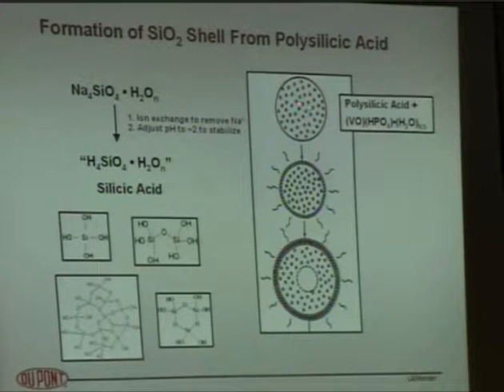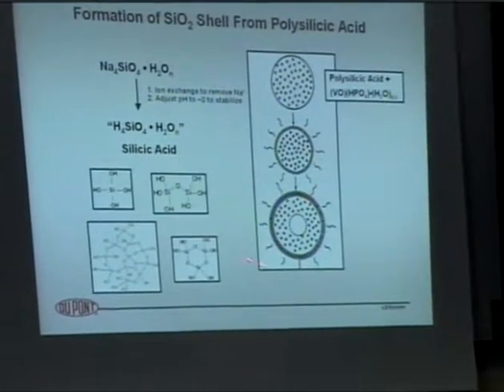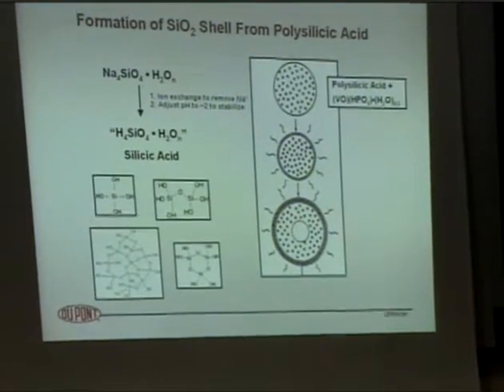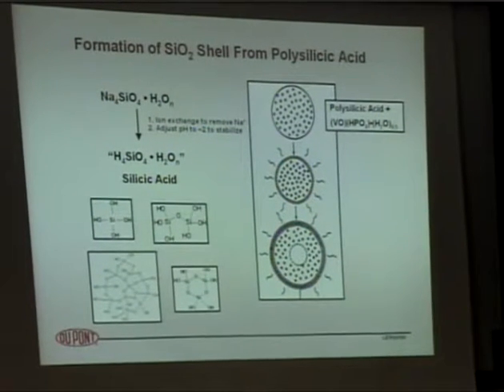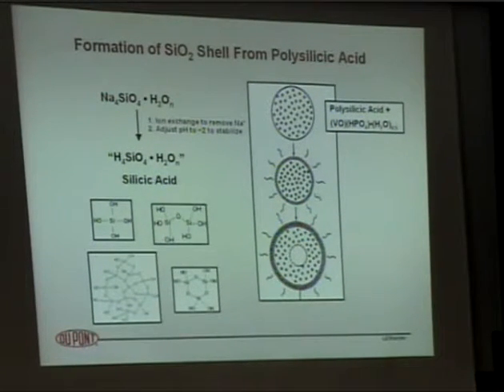Then he took that aqueous solution of silicic acid, put it into a spray dryer, along with granulated, micronized, powdered VPO catalyst. And in that spray dryer, the water moved to the surface, carried the silicic acid with it to the surface, dried, and created a very strong, very porous silica coating on the surface of the catalyst. So you ended up now with a catalyst pellet, the right size for a fluid bed or a transport bed reactor. The silica was on the surface, very porous. Butane, maleic could go through it very, very nicely, but did not affect the selectivity at all.